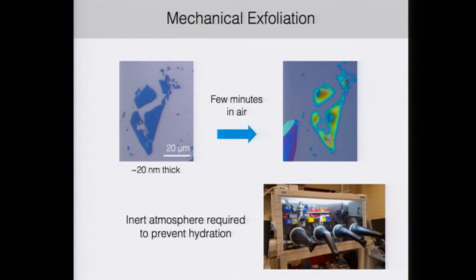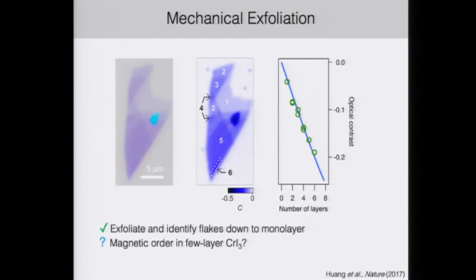So over the past several years, we've made a lot of efforts in our lab to develop techniques to fabricate devices from air-sensitive materials such as chromium triiodide inside our glove box, since we can't use all of the conventional techniques performed out in ambient conditions. Once inside the glove box, we're able to identify crystals down to the monolayer limit of chromium triiodide using optical contrast in the microscope images. And now we want to see, what does the magnetic order look like in few layer chromium triiodide?